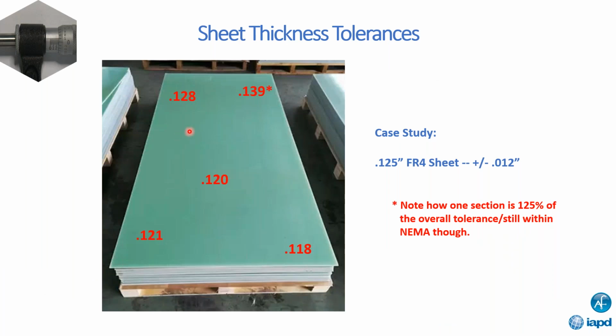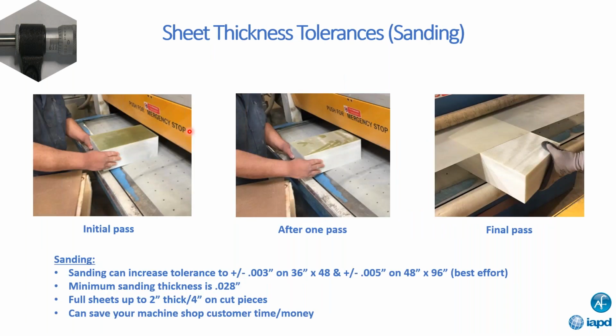If you look at this example here, starting in the upper right-hand corner, this is an actual example. This sheet measured out at 139, 118 in the bottom, 121, 120 in the center, and then 128 in the upper left-hand corner. You notice the one with the asterisk, that's actually outside of that plus or minus 10%. But keep in mind, our materials per NEMA have a pretty wide open tolerance, kind of like acrylic, but they have some extra tolerances because of NEMA's 125% on another 10% of the sheet. A lot of numbers there, but keep in mind just that the tolerances can vary.